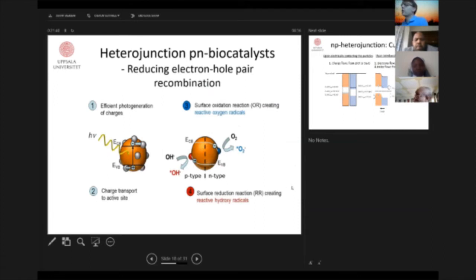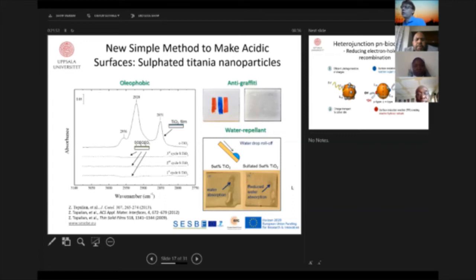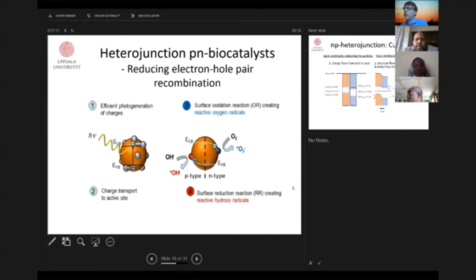So this is, of course, one way to do it, that you modify the texture of the catalyst, that you add some chemicals and some molecules at its surface to combat these deactivation problems. But still the efficiency is fairly low, as I said initially. So one strategy which is common, and I would say the majority of the research being conducted today belongs to this class, which is my last section, where they chemically, by doping, try to modify the structure of the catalyst for many purposes, both for reducing electron hole pair recombination, as we do here, but also for visible light activity to exploit a larger portion of the solar light. I will focus here on reducing electron hole pair recombination.